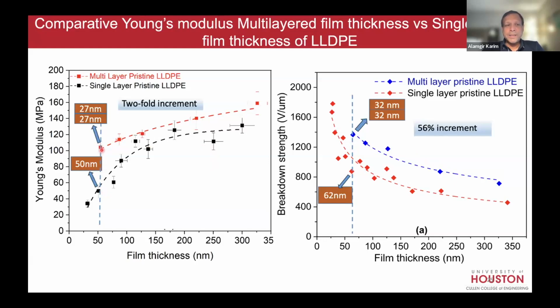But if you want mechanical strength, if you stack two polymer films in this ultra thin regime that is the same thickness as a single film, modulus is much higher. It goes from 50 to 100, doubled. All right. Same with the breakdown voltage. The 60 nanometer is down here at 900, and here this is about 1200, 1400 if you make the ultra thin stacked bilayer.